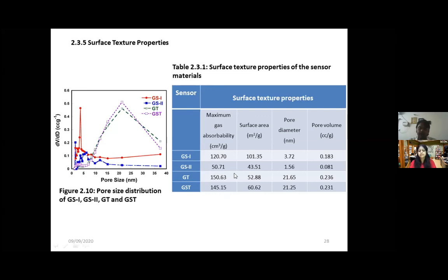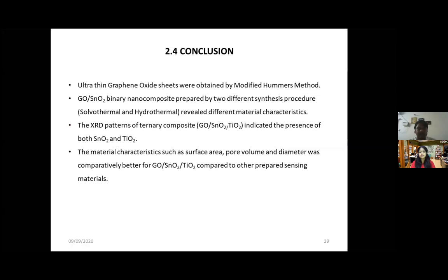So for GT, the maximum gas adsorbability is higher compared to GST, which is 145.15 centimeter cube per gram. So this is the gas adsorbability of that particular material. Coming to GS1 and GS2, GS1 possesses double the surface structure properties compared to GS2 here. And all these properties, starting from XRD, microscopic images, FTIR, and surface structure properties, indicate the favorable deployment of these sensor materials for fabrication and further validation here.